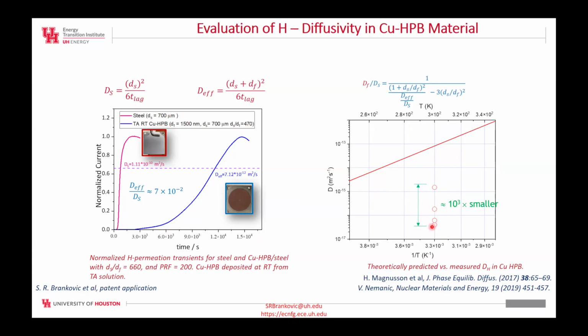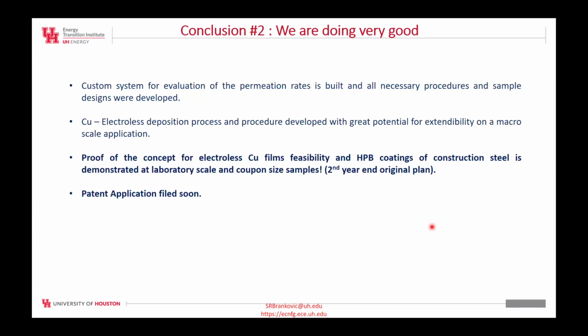So that means that our copper actually, besides being the right material, also is the copper that has a very special grain boundary composition with a lot of hydrogen traps, which retard the hydrogen permeation through it, and actually it even acts better than the regular copper. So we're doing very good. We right now, you know, patent application will be filed soon, but the proof of the concept is done.